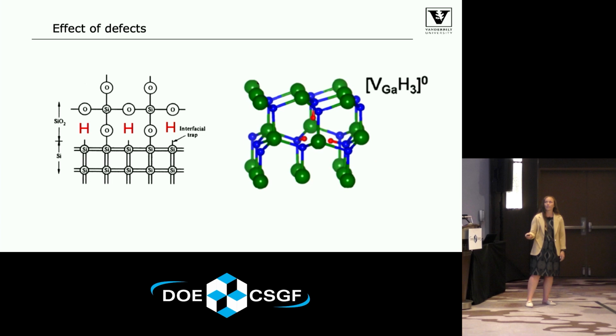And here I show that hydrogen has come in the fabrication process and passivated these defects. So it makes them to where they don't interact with the carriers as much, they're not going to trap them, and we call those deactivated defects. What we care about is when the system gets excited, it starts vibrating, and that hydrogen gets kicked out, then the defects become active. Carriers coming by the defect will likely get trapped there, the device degrades, and we want to figure out what makes those hydrogens get released, what process leads to that.